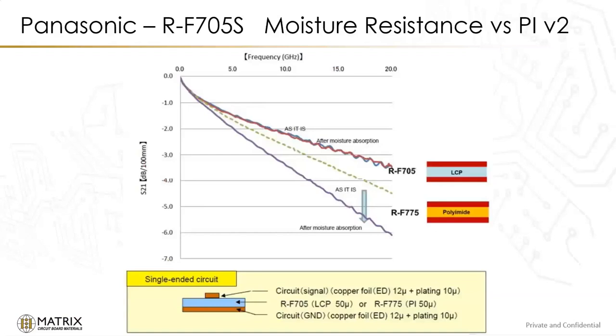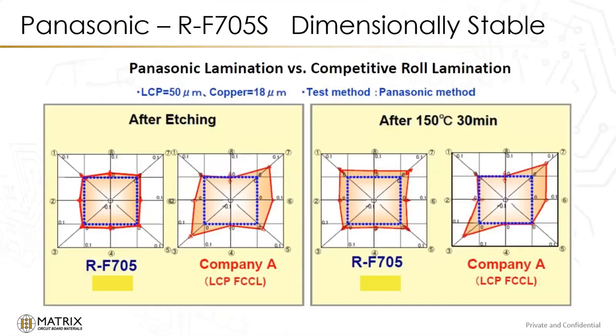Another way to look at that too is against moisture. So the moisture absorption, we see the LCP, the two conditions as is, and after moisture absorption, they almost line up right on top of each other for LCP. And you can see between the polyimide, the as is versus the moisture absorption, there's a degradation in the loss factor with that. So there's more loss. So the LCP is very stable across temperature and across moisture. And then processing-wise, it gives some real advantages as well.